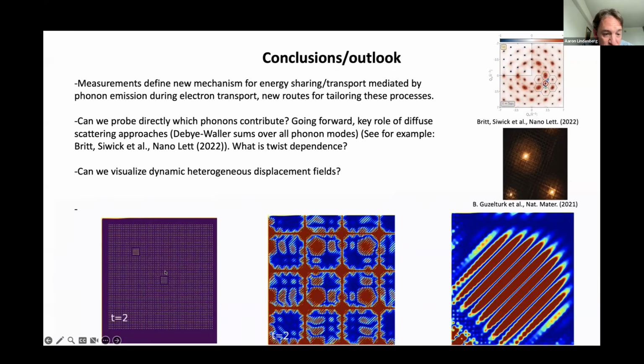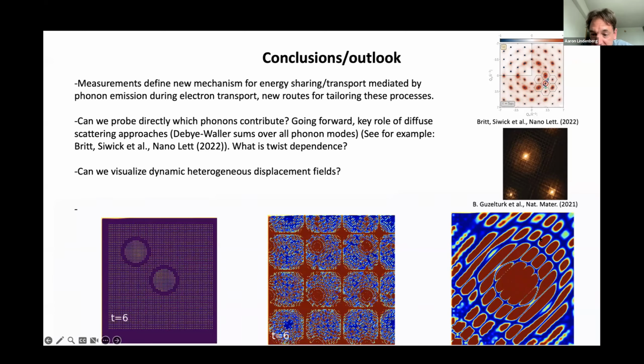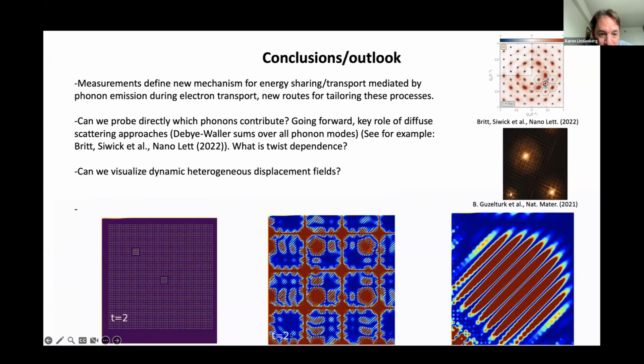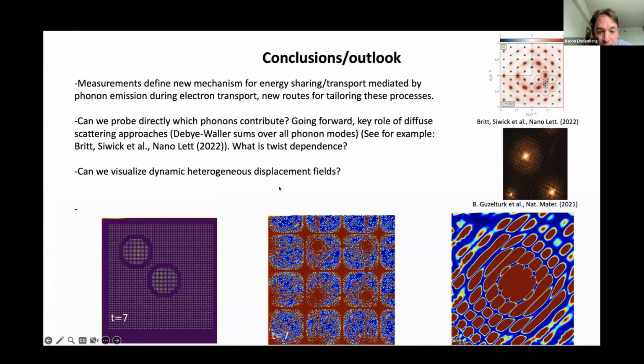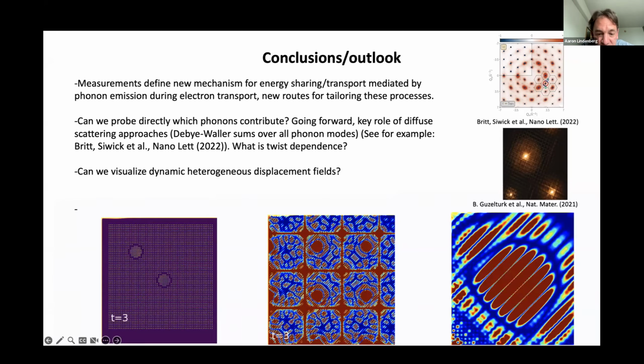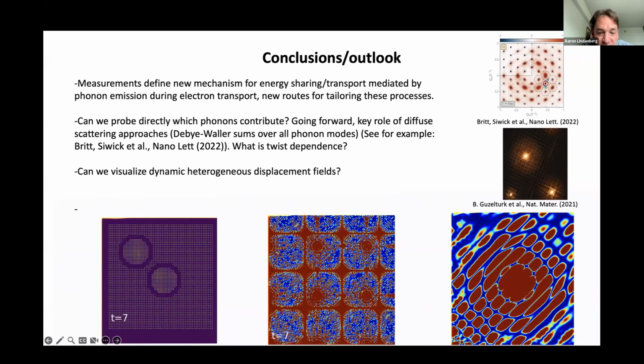When you have two distortion fields, you get interference effects, as shown here on the right, and so on. So there's an amazing amount of information. There's never been an experiment, as far as I know, that has had the signal to noise to directly access all of this information in the diffuse scattering. There may be a few heroic first order experiments pushing in this direction. But this is, I think, really a key direction going forward in terms of visualizing this kind of dynamic heterogeneity.